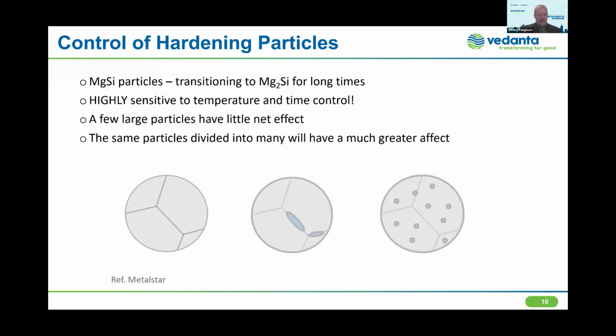So I'll show a little graphic here. On the left-hand side, let's imagine we're looking through a microscope at the microstructure, as we call it, of the aluminum, and we see little or no magnesium and silicon particles. If we are out of control, what very often happens is we get equilibrium Mg2Si phases, and we'll get few of them, and there will not be very many. And these have very little positive effect on strength.